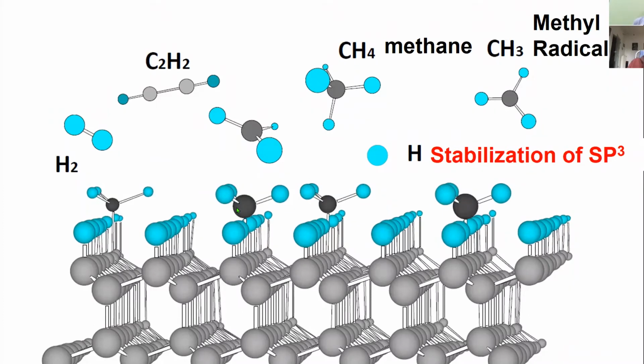For how to get the layers of diamond, we use methane in this case, and the methane is decomposed into methyl, which is CH3. It's a planar structure. Some of the hydrogen-terminated diamond points are replaced by methyl, and then we get one monolayer, or one layer, of the carbon phase.